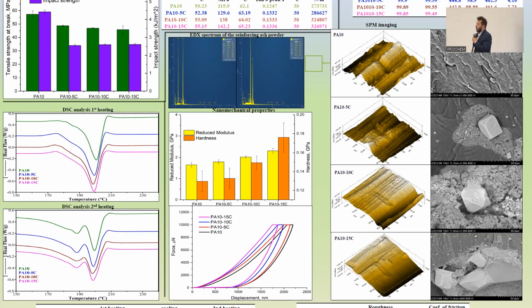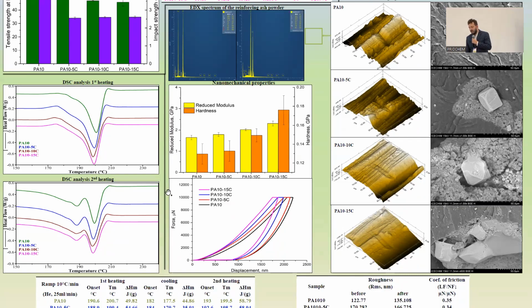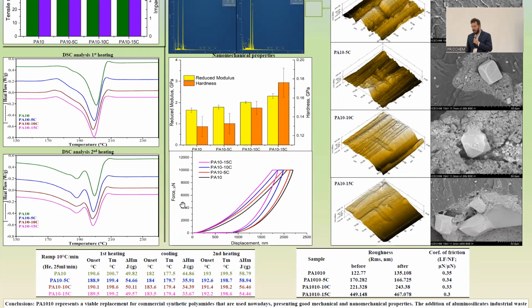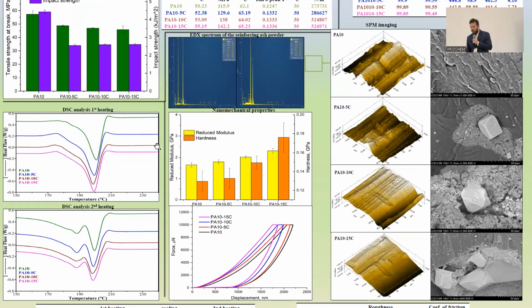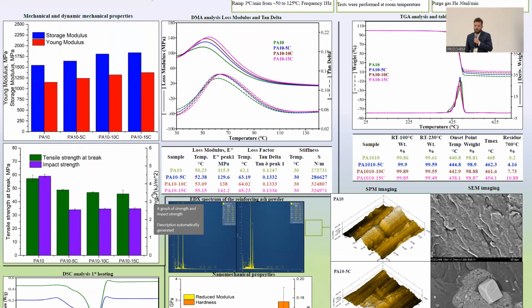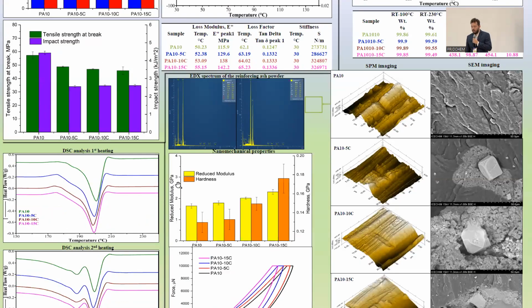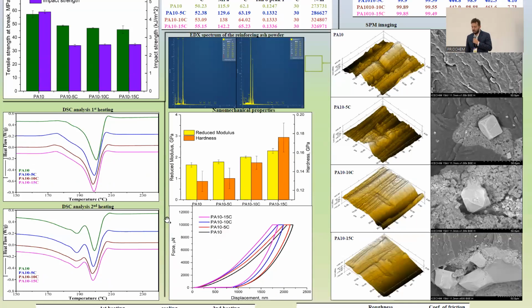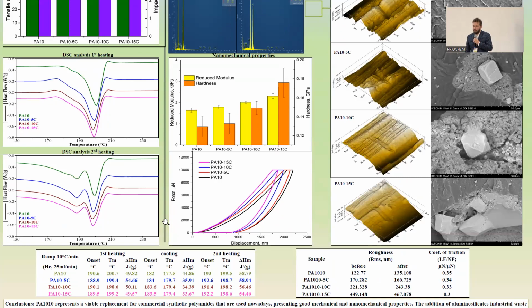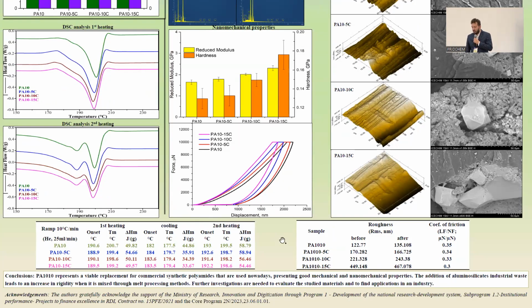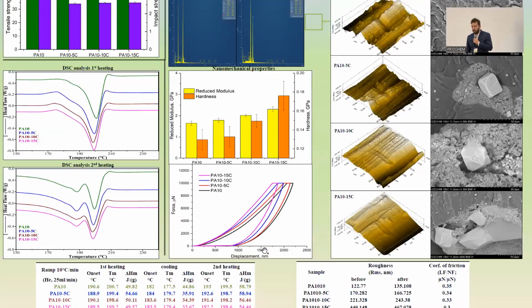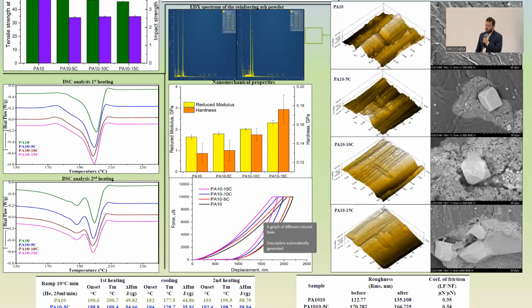Now, from the viewpoint of nanomechanical properties, nanoindentation showed an increase of reduced modulus and hardness for the composites compared to bio-based polyamide 1010. And even though we have a decrease in the elastic recovery of polyamide 1010, this increase in properties correlates well with what we've determined earlier regarding the mechanical properties. And so our materials become rigid when we introduce this ash filler in our polymer matrix. We also see an increase in surface roughness and for the coefficient of friction, meaning that the composites are more